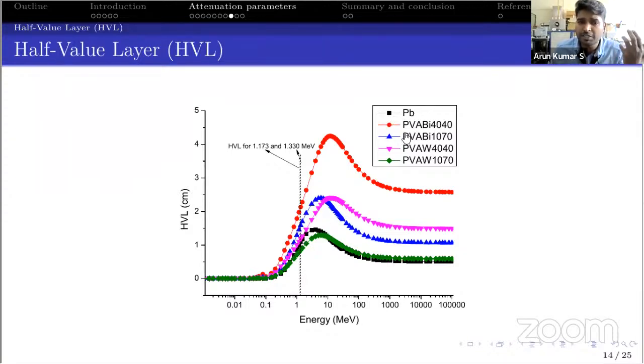Here you can observe that the black line indicates the half value layer of the conventional material, lead, whereas the green line is depicting the 70 weight% PVA tungsten composite, which is much lower than the lead. And I would like to point out one more thing. You can observe that even the 40 weight% filler rate PVA tungsten composite is giving almost equivalent to the lead. I mean, you don't need to go even to 70%. Even with 40%, you can get more or less a half value layer equivalent to the lead.